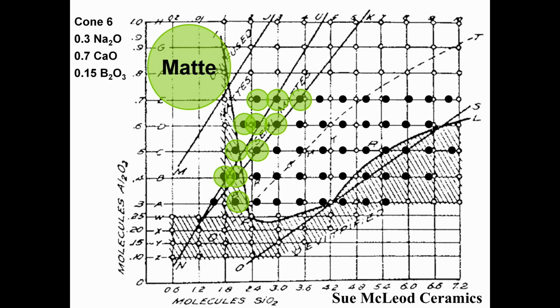To make a true matte glaze, Stahl found that you need a low silica to alumina ratio, generally 5:1 or below. Look at the hard diagonal line of green circles that moves straight up the line that Stahl drew. This is the 5:1 matte line. My results line up exactly with the research that was done over 100 years ago. Science, very, very cool. All glazes on this line have a silica to alumina ratio of 5:1. As soon as the ratio went above 5:1, the glazes were no longer matte and started to become glossy. So, Stahl's map can be used to predict a matte or glossy surface according to the silica to alumina ratio.